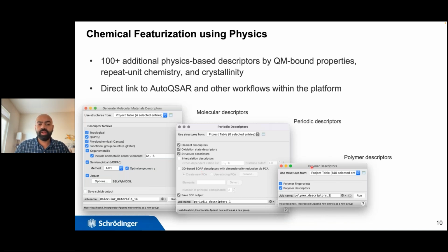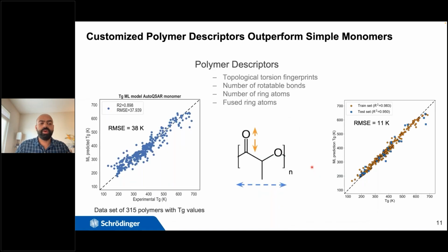And similarly, we have a panel which can also generate polymer fingerprints and polymer descriptors to improve the performance of machine learning models that are specific to polymers. So a concrete example of polymer descriptors is shown in this example here, where we took a data set of around 315 polymers from the Bicerano Polymer Handbook. So we made machine learning models using AutoQSAR without providing any additional descriptor, so basically treating the polymer repeat unit as just a molecule. When we did this, we got a root mean square error of around 38 Kelvin for the glass transition temperature.